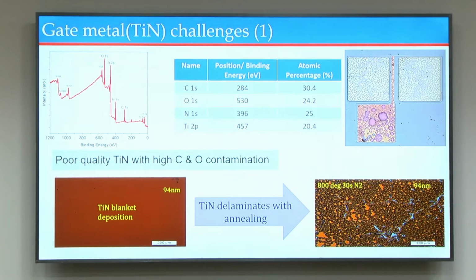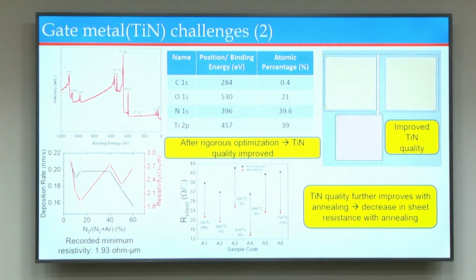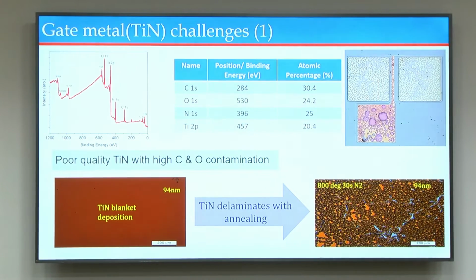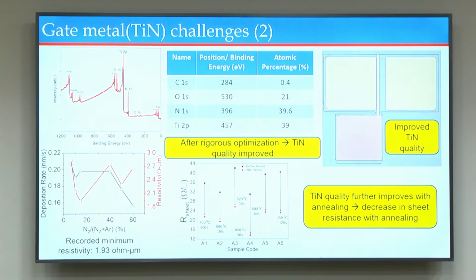For example, in this case, the quality of the TiN, titanium nitride. So we have this titanium nitride gate, and if you don't control the titanium nitride gate quality in terms of the contaminations, you have these kind of bubbles formed when you do a high temperature process. Now in terms of transistor performance or the sheet resistance, there was not much change, but if you don't notice this, you have these kind of issues formed when you do a high temperature process, right. So a strict optimization of the gate metal or the source drain is also important. So for example, if you see in the previous slide, you see the source drain metal region as well as the gate metal region, the quality is not that good, but when you do this strict optimization in terms of contamination control of carbon and oxygen across these metal stacks and proper recess optimization, you get much better quality source, drain and gate.